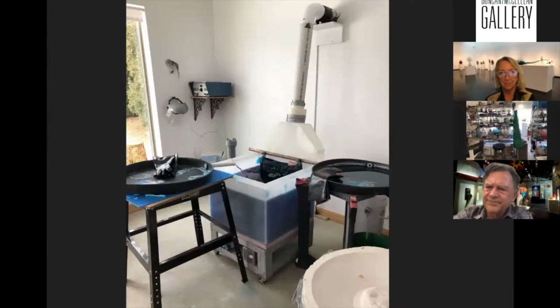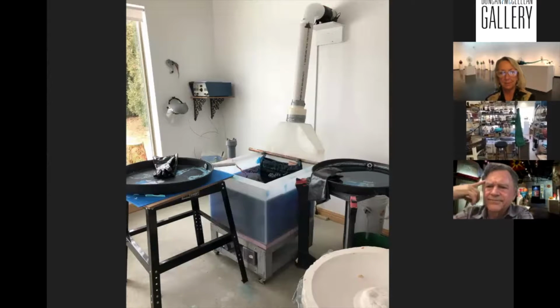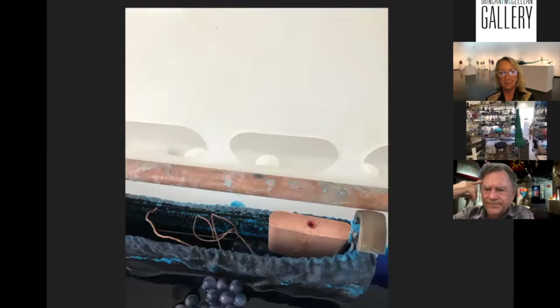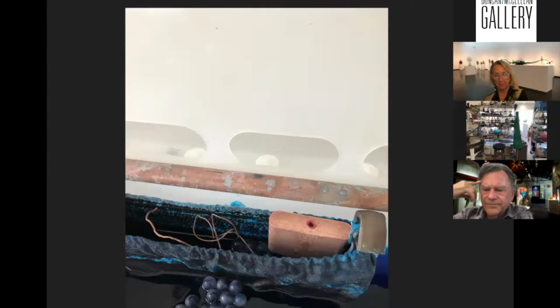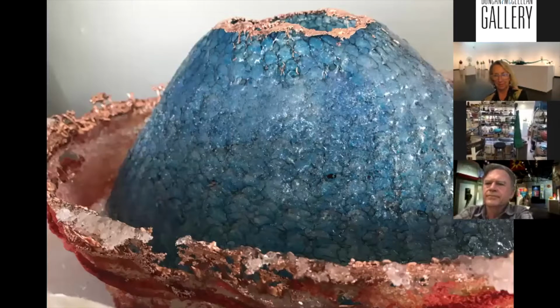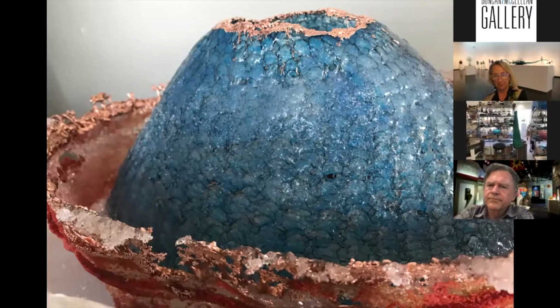And then the halves get electroplated. That's my electroplater, as I showed you earlier. That puts the copper onto the piece. That there is a copper bar that's in a basket in the acid, and that will break down to a molecular level and redistribute onto the glass wherever the glass has been painted with an electroconductive paint. So that's the halves. It's painted on the edge and ready to go into the plater.